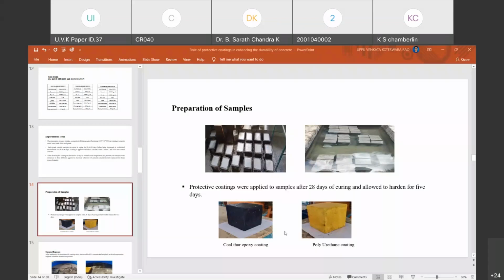Mainly, we already know that polyurethane coating is famous for resisting corrosion, and the coal tar epoxy coating is to resist sulfates or acids. And this is the chemical exposure I have done. I have taken the sulfate solution, MgSO4 solution of 10% concentration, and the acid solution, H2SO4 solution of 10% concentration. And this is the experimental setup of the rapid chloride ion penetration test of M20 with polyurethane and M20 with coal tar epoxy, and M30 and M40 samples without protective coatings.